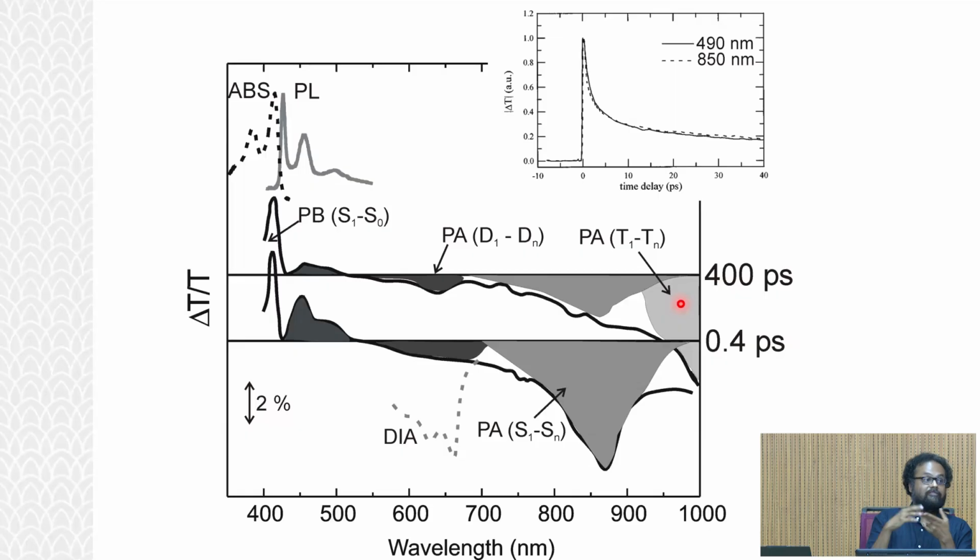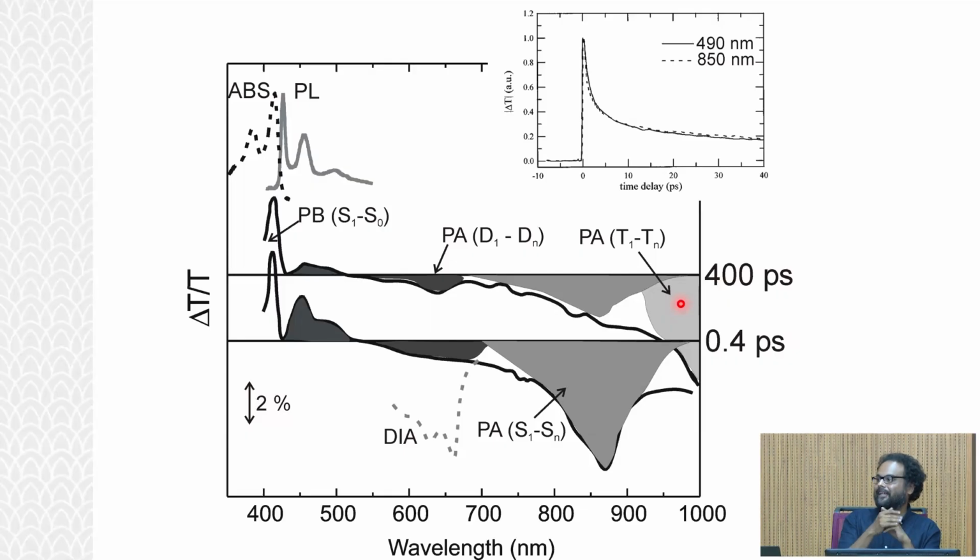For example, if I want to know where the charge species band is, there's one way of knowing it. Just dope the system. Put charges there, see where they absorb. Then you know this band is a charge band. And there are other tricks that you can use to figure this out. But that's the job of any spectroscopist, to assign these bands. And that is non-trivial. That's the point that I'm trying to make. And it's very strongly a chemistry problem.